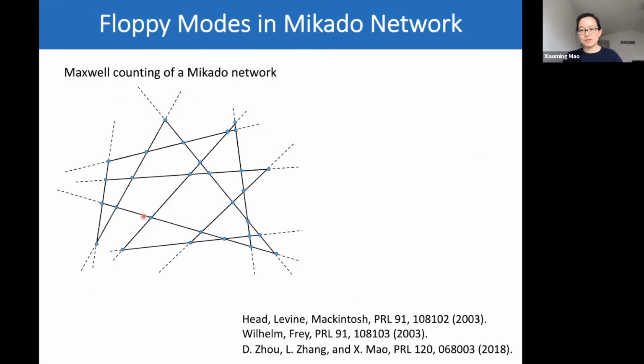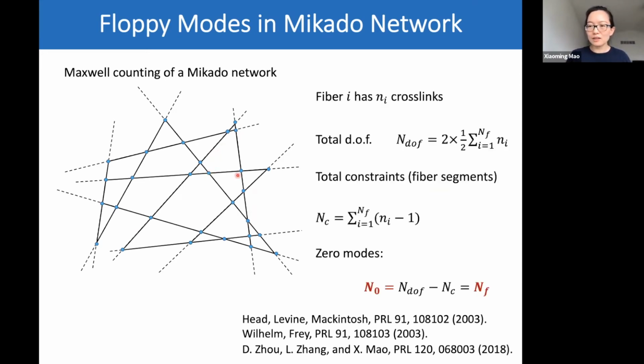To study that, we started from the so-called Mikado network model, which is a more general model than diluted lattices. There is no underlying periodic lattice. The Mikado network is constructed such that you throw a bunch of straight lines on the 2D plane and put down a cross-link whenever they cross. Then in the central force limit, if you just consider these as springs, you can do a Maxwell counting and find that the number of zero modes is exactly equal to the number of fibers.